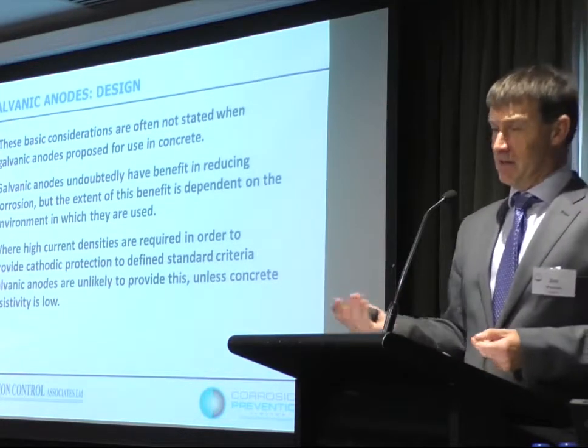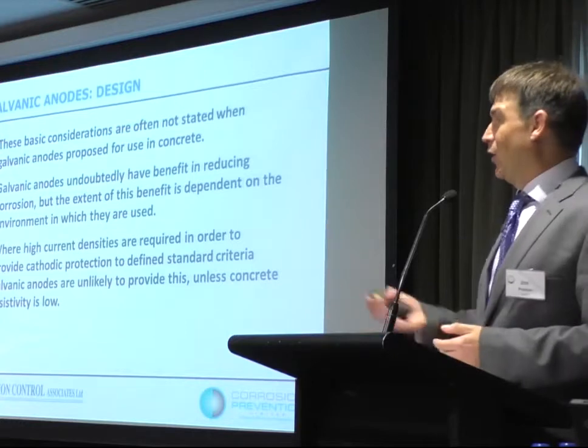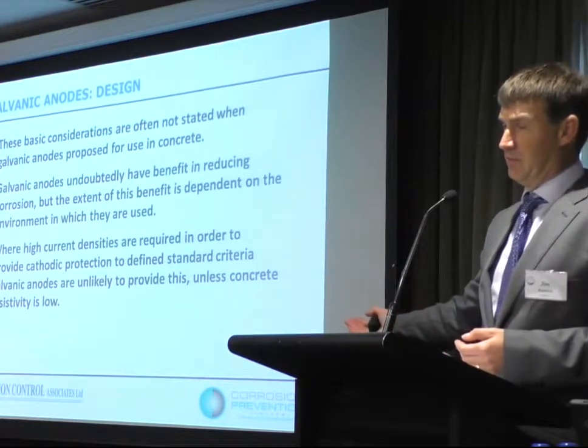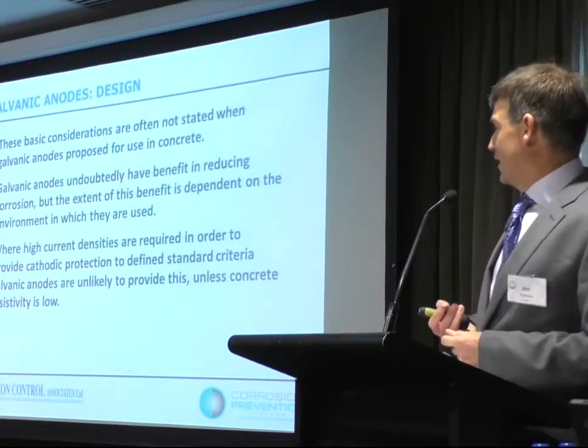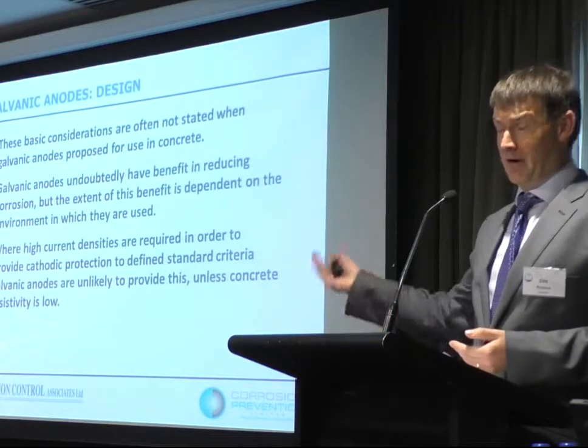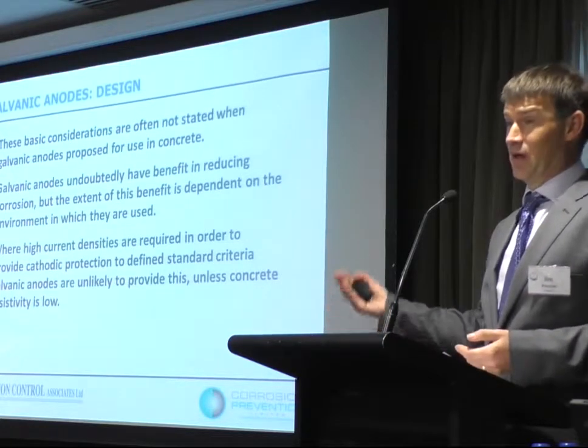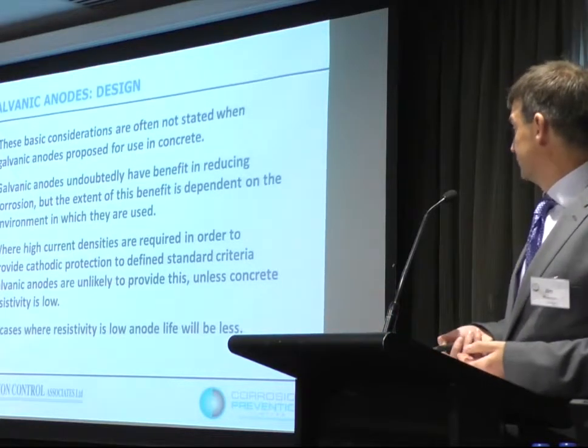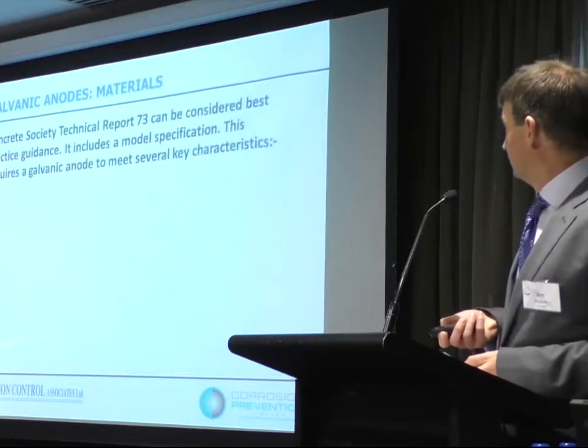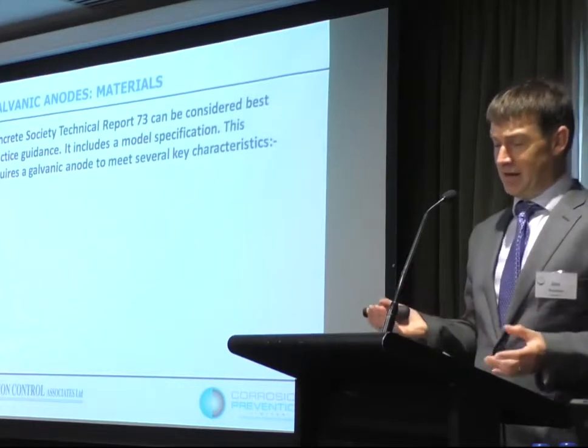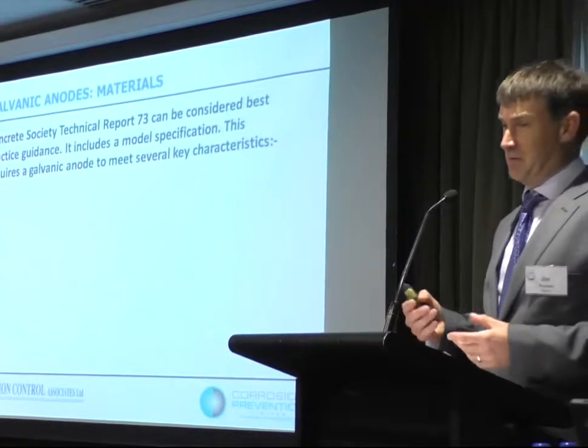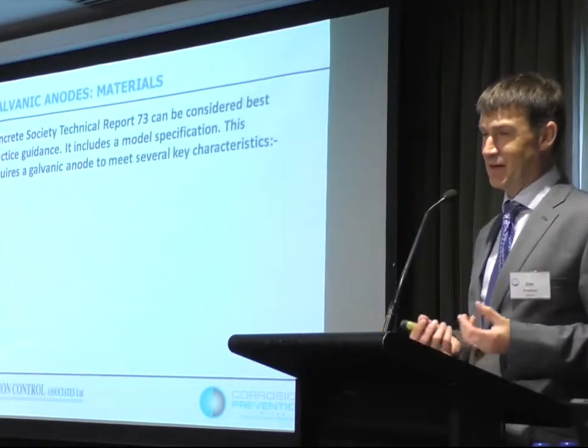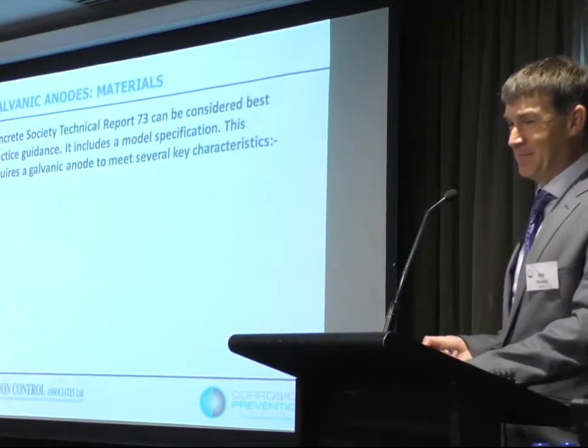If we need a high current density, if we need to achieve cathodic protection, we're not going to do it with galvanic anodes. If the resistivity is very low, then we might get close to doing it, in which case the life of those anodes is going to be low. So that's the design. I'll come back quickly to my galvanic anode, because I'm going to make a fortune out of these.